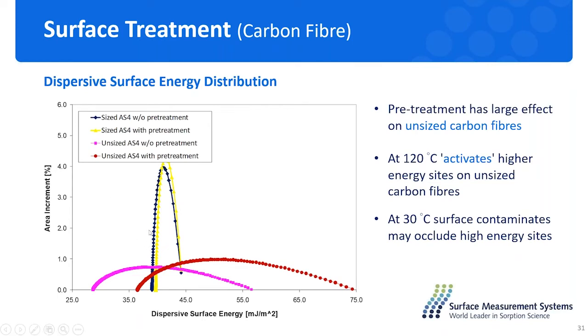Whereas for the sized carbon fiber, which is the blue line and the yellow line here, the two are almost overlapping. That means the sizing agent is acting as a protective layer to protect the carbon fiber inside from the temperature effect, making the sample or the fiber more stable or more uniform during applications.